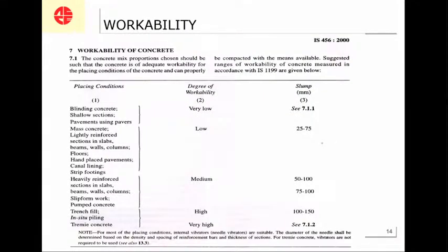These are the workability conditions, but this I would say is more or less very theoretical in nature. See, 75 to 100, for example, indicates a medium degree of workability, but sometimes in sites you will understand that 100 mm slump even causes segregation. It is highly workable. Sometimes it is flowable also when you vibrate it. So it is all relative. It is all indicative. You will understand the meaning of it when you actually experience it yourself with concrete. You touch concrete. You supervise concrete. The more and more you are with concrete, you will understand these numbers in a different perspective.